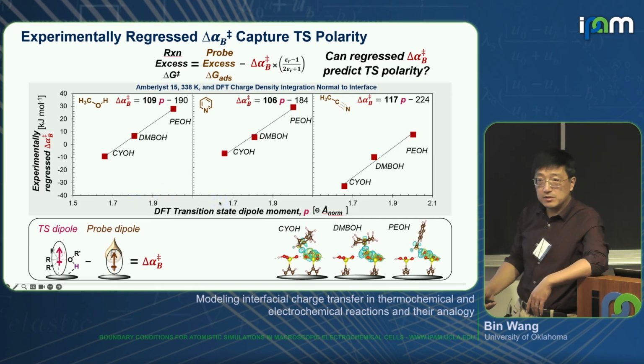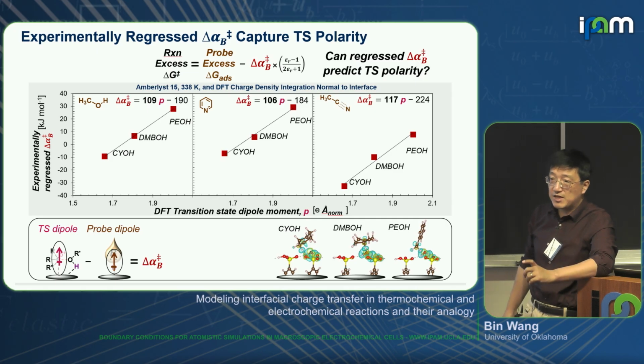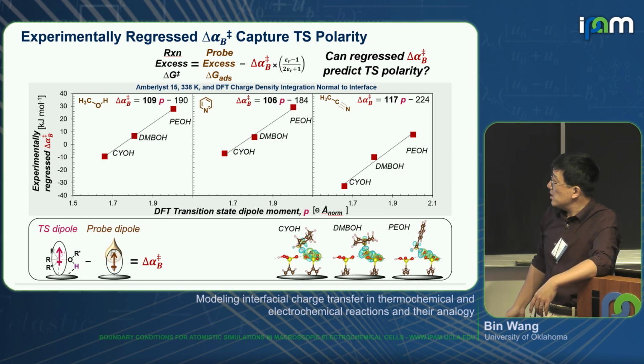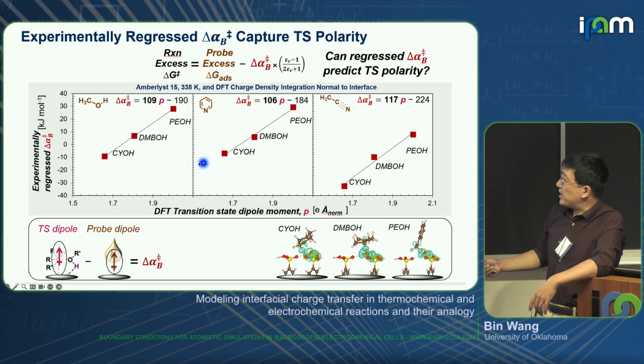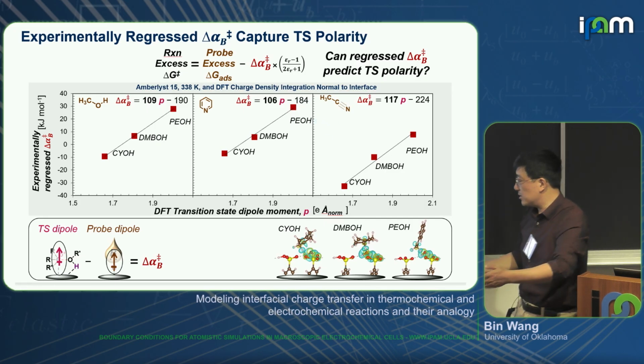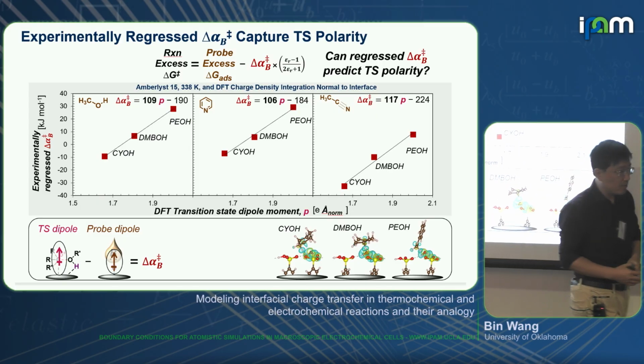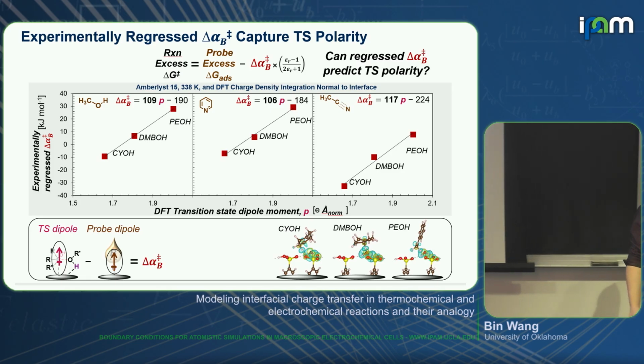That in fact makes a lot of sense. It depends on the strength of the dipole at the transition state. If the dipole is large, or the charge transfer is large, then it's more sensitive to dielectric screening, and vice versa. I show 3 different figures just by changing the probing molecule from methanol to pyridine or acetonitrile, but the general trend is the same. The key concept here is how to stabilize this transient dipole for acid-catalyzed reactions.